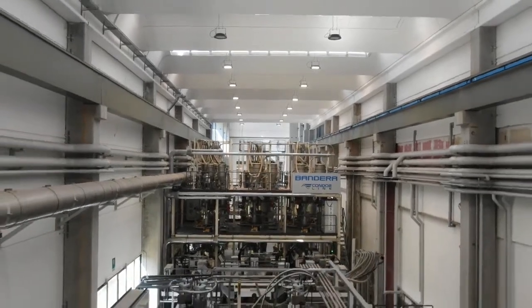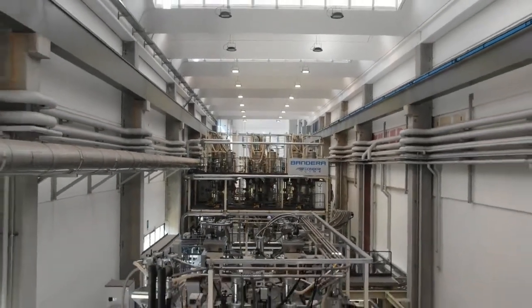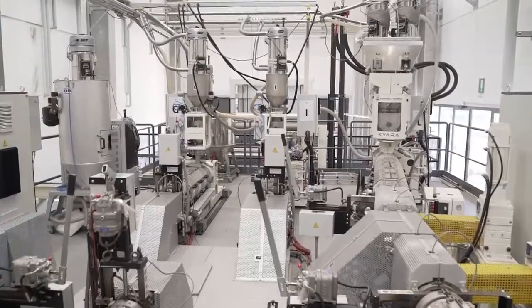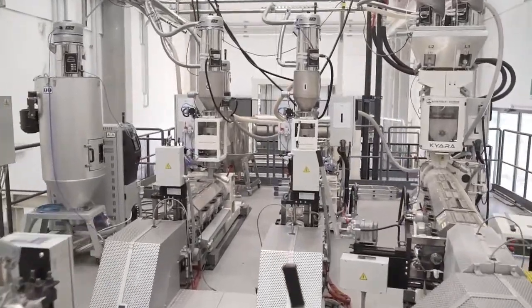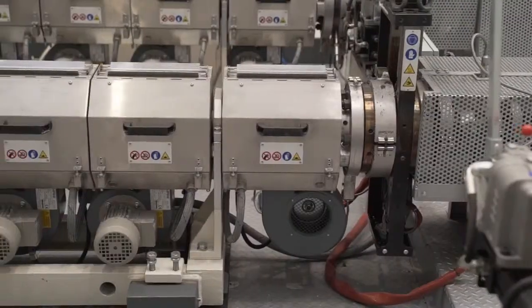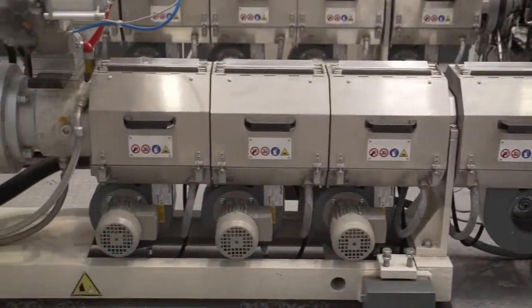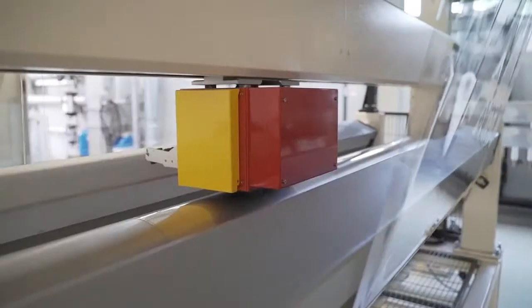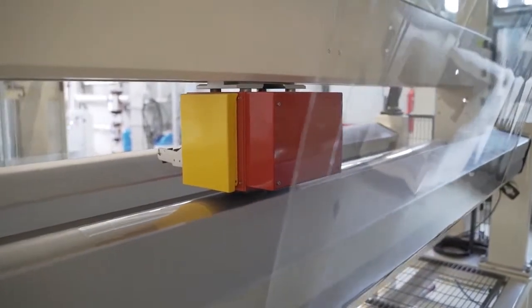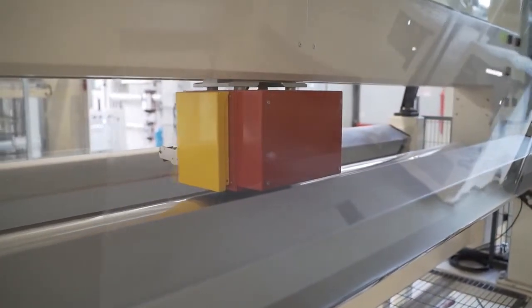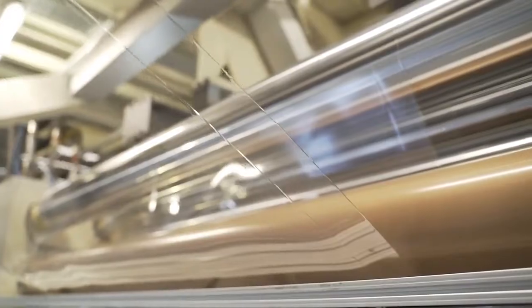Downstream the substrate zone, the 9-layer coating station is equipped with single-screw extruders to customize the final product structure in order to meet customers' needs. The extrusion coating configuration allows the production of very thin and accurate layer thicknesses, up to 1 or 2 microns, delivering amazing quality and flexibility, above all compared to traditional co-extrusion design.